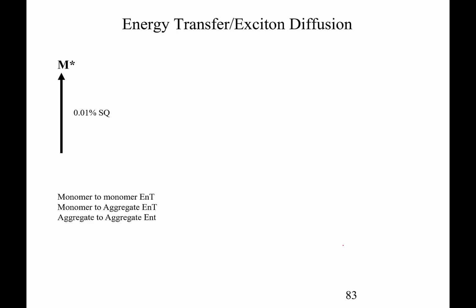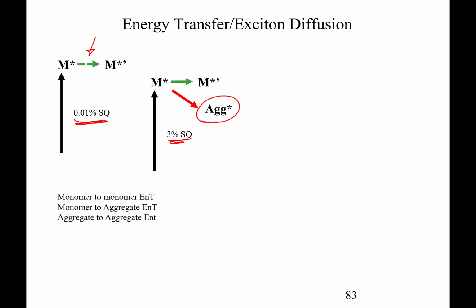So here's a summary of what's actually going on. Here's our monomer excited state. And what happens at very low concentrations is we do get some energy transfer, as represented by this dotted line arrow in here. Of course, as we start to increase the concentration, the rate of that monomer to monomer energy transfer, rather, not charge transfer, increases. But we also start to get a formation of an excited aggregate state as the concentration increases and those molecules start to talk to each other.